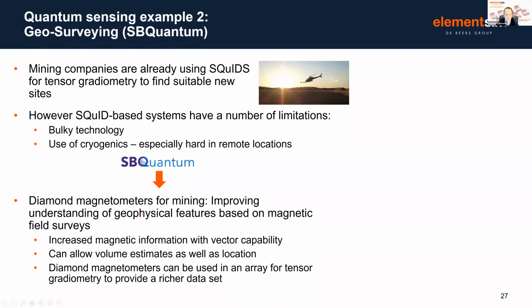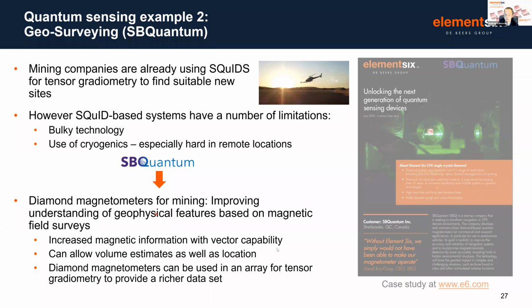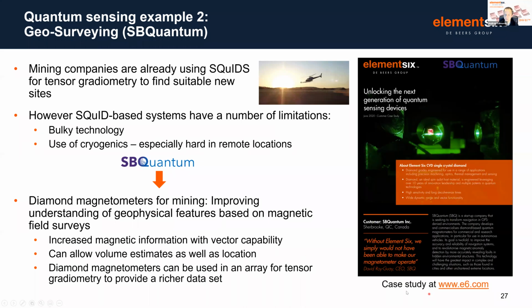So in the case of diamond magnetometers, we have exactly the same benefits that we've discussed on the last slide in terms of having that intrinsic vector capability when we have an ensemble of NV sensors. But the further information that you can get by building an NV sensor are things like the volume of material that you're dealing with, as well as the location. And ultimately, SBQuantum are looking to build diamond magnetometers into an array of sensors to perform tensor gradiometry to ultimately provide a richer data set. Now, for anyone interested in further information on this, we've put together a nice case study between us and SBQuantum that you can find on Element 6's website.